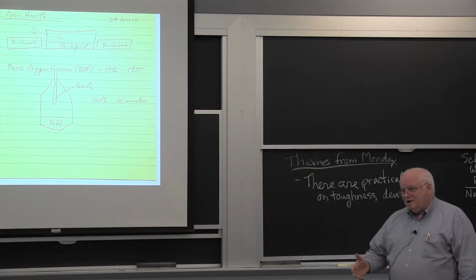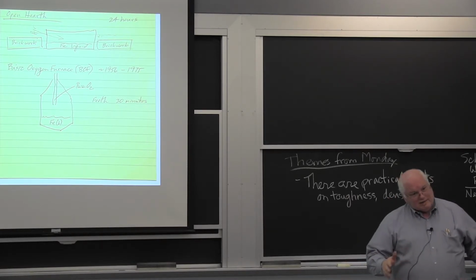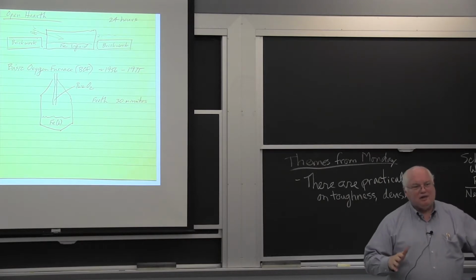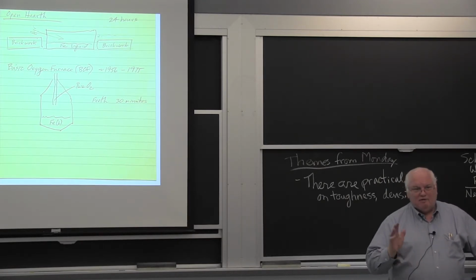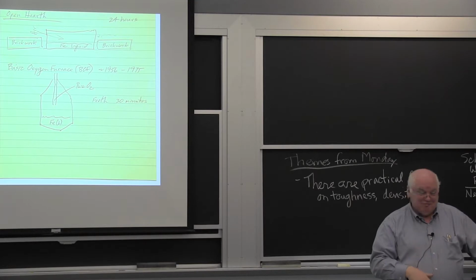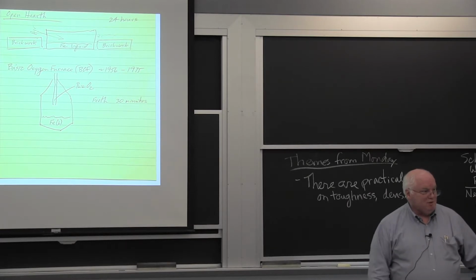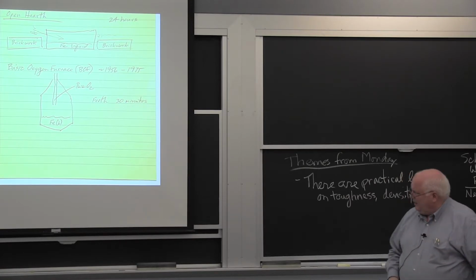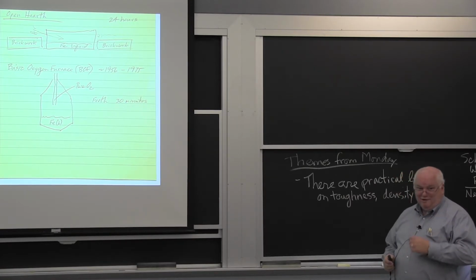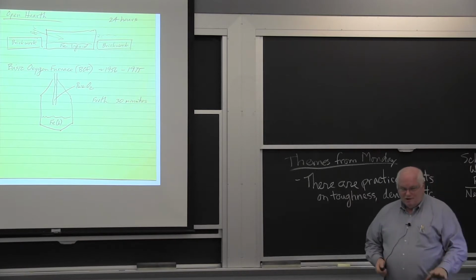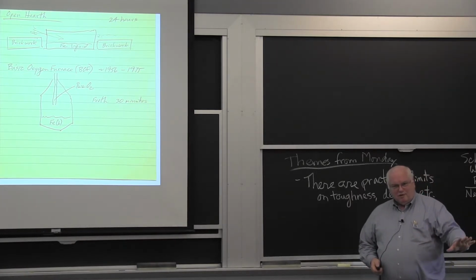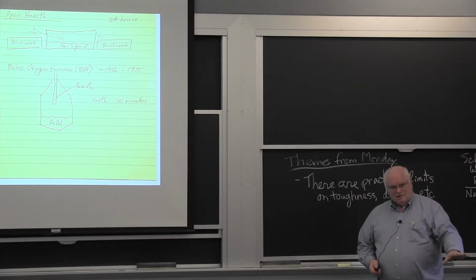Now, the floor of the casting shop is usually just dirt, but it takes about a week to clear that up, and $5 or $10 million. Okay, because you sort of now welded all your steel parts in your cast shop with this big puddle of 200 tons of molten steel, which solidifies. You have to wait for it to solidify, and then you have to go in there with oxygen lances and cut it up. Both of them lost their job. Okay, but the moral of the story is, have enough respect for that hourly employee and listen to what he means when he says "but."